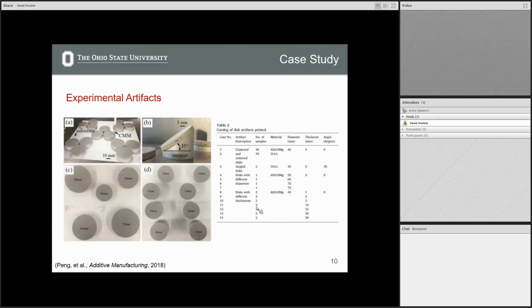Why such a huge variation? Is there a reason why you're focusing on this? Our primary sample was this 45 millimeter diameter, 5 millimeter thickness sample, because via pilot studies, that's somewhat in the deformation range that we were looking for. It was where we could start to pick it up in the CMM, but we weren't getting so far out of some basic beam bending and linear analyses. We didn't want something that would pull up like this. So we printed a lot of these.